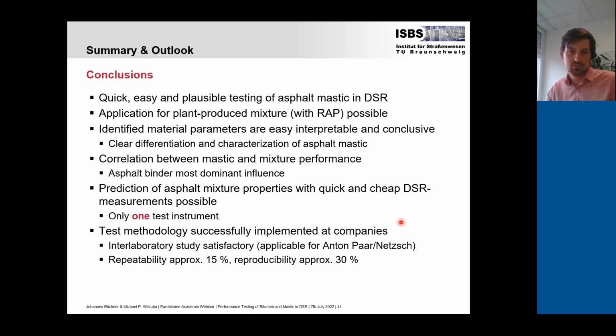The identified material parameters are easily interpretable and conclusive, so you know exactly what is a preferable material behavior and what is less preferable. There's a clear differentiation and characterization of asphalt mastic. We have a correlation between mastic and mixture performance. Asphalt binder is the most dominant influence factor here, so that's why we now continue to look more on the